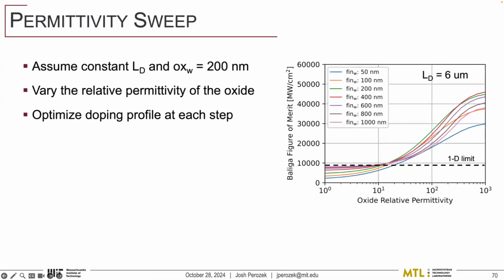Running with this, it's way faster than using commercial software because we were able to tailor it specifically to our devices, and we can do massive sweeps of the design space. We kept things, again, something that we could fabricate. So we didn't go with oxide thicknesses greater than 200 nanometers. All of these are deposited by ALD, so any of the staff back there that sees that would have a heart attack even talking about 200 nanometers.